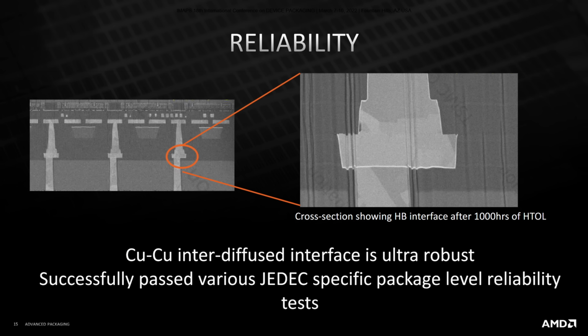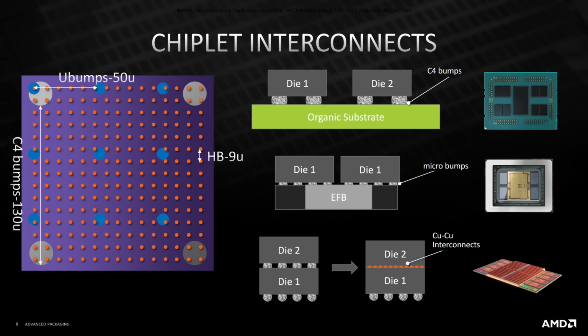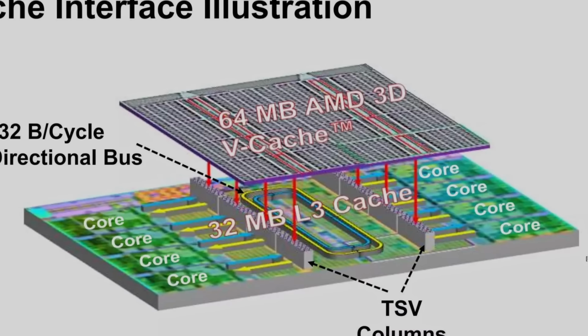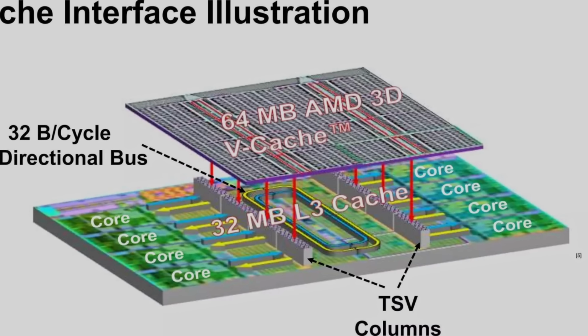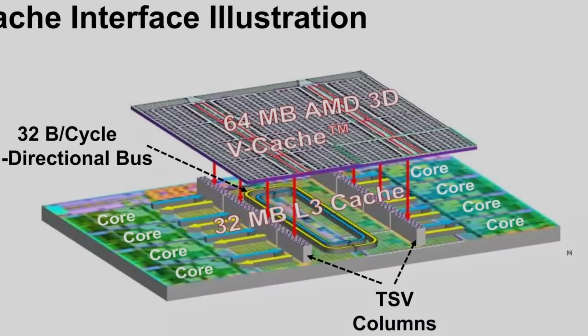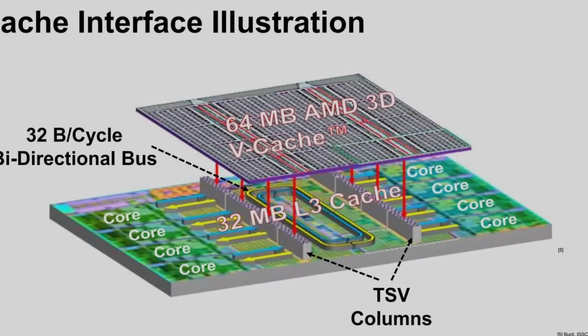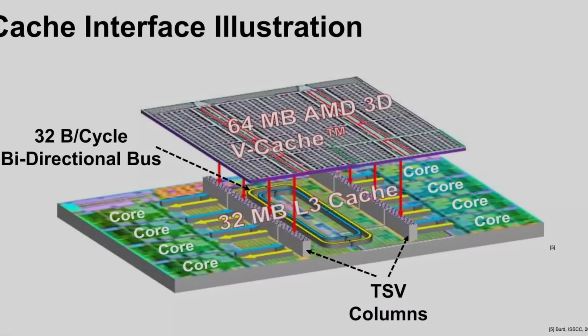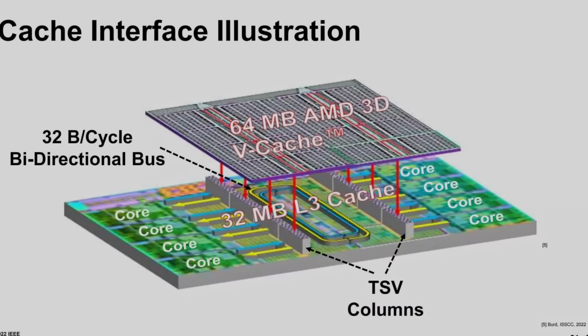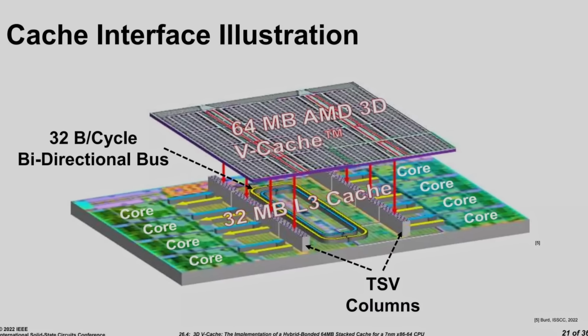The second advantage is that placing two chips directly on top of each other and not having to use layers of microbumps and solder in between also reduces latency. A hybrid bonded chip can have shorter access times to parts of the chips below or above it than even some areas inside of that very chip, because the signal only has to travel vertically. That's what allows AMD to extend the L3 cache of its X3D CPUs, because the cache chiplet, no matter if above or below, is so close, almost as if it was on the same die.